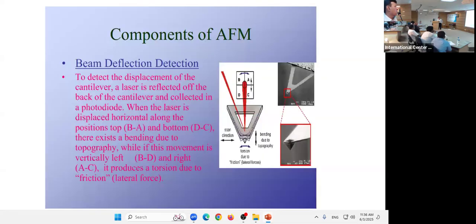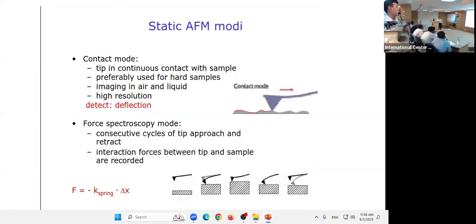This is the beam deflection that we discussed, that the laser is bombarded on the tip, and then it is reflected, and you will see that it's going up to the photodiode detector. This is the contact mode, the static mode, which I mentioned is used for those samples which are tightly bound to the surface. But if your materials are not tightly bound to the surface, then do not use this one. Otherwise, you would not get the desired information.